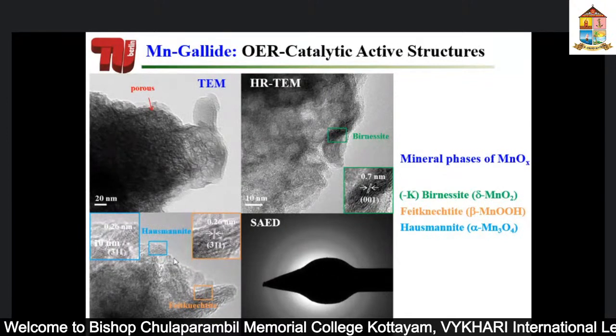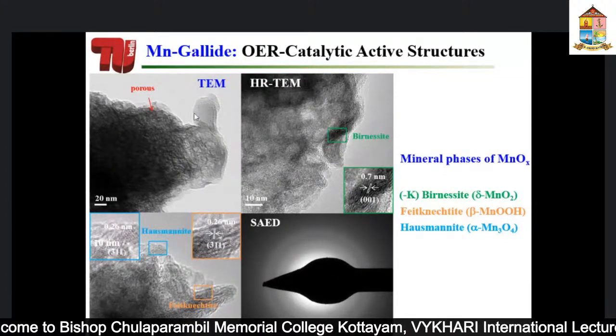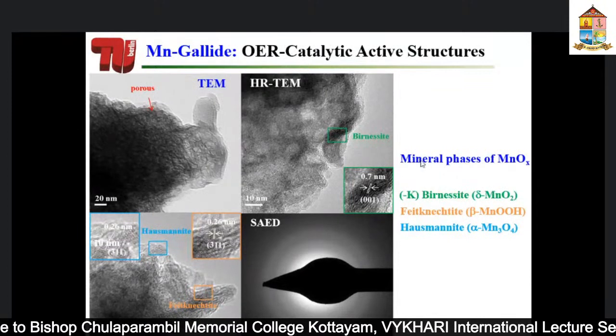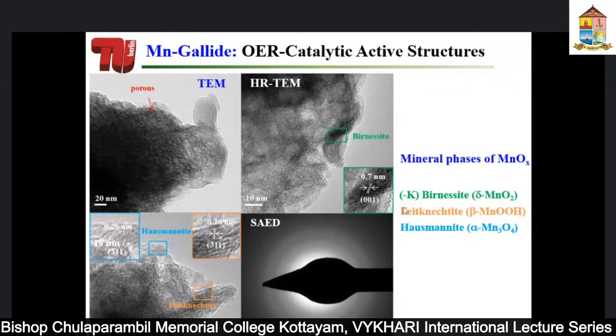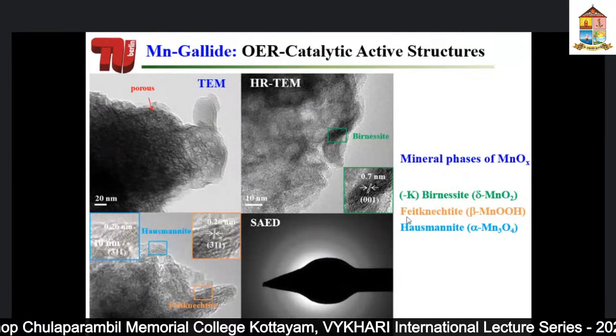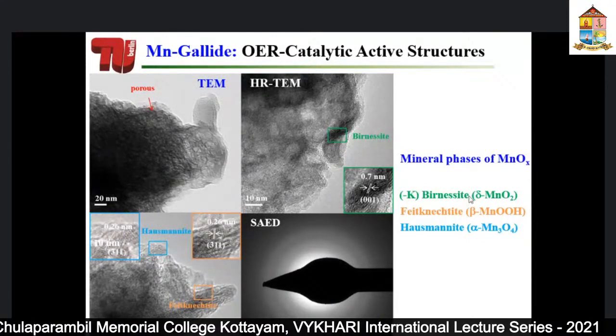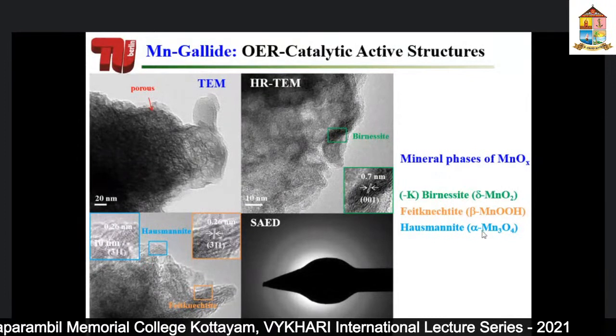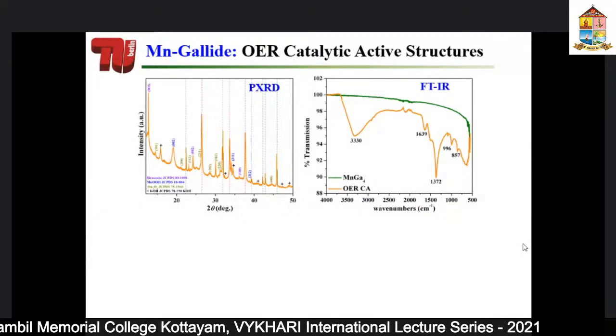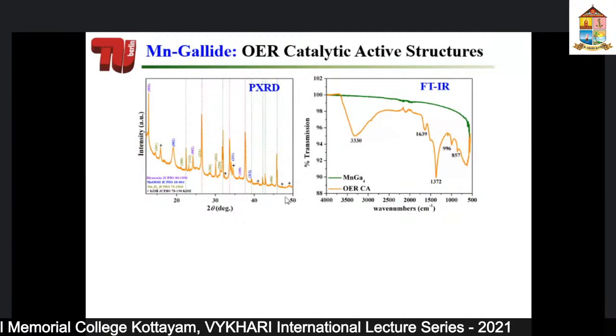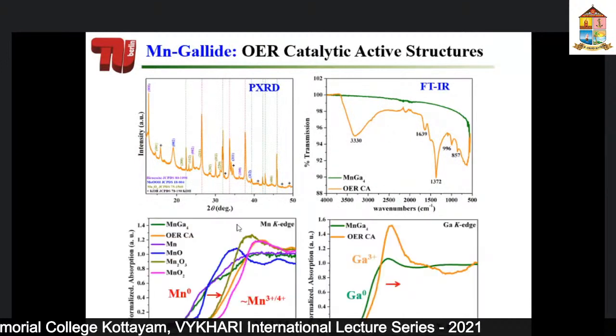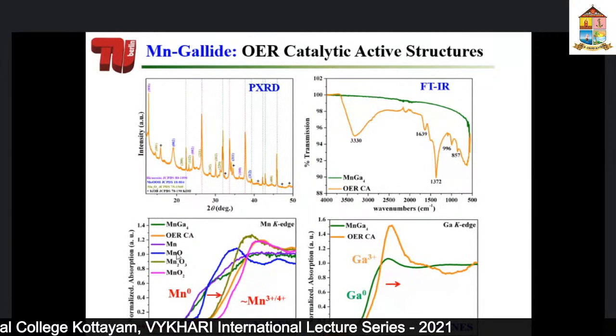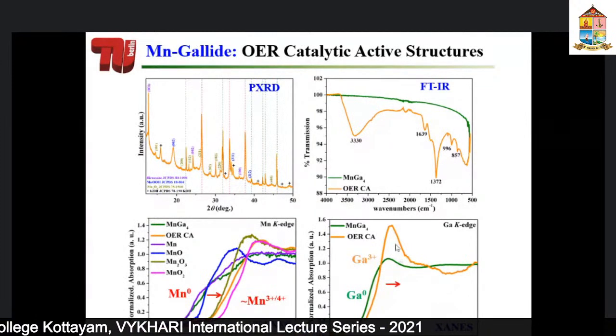And they form three different types of structures. So from one, we start with the manganese gallide. At the end, you are forming a mixed material with delta MnO2, beta MnOOH, and alpha Mn3O4. We also did other characterization measurements, XRD, IR, and also the XANES measurements for gallium. In each case, the message was the same, that the material is not stable under these conditions.